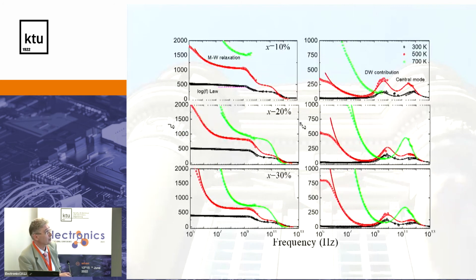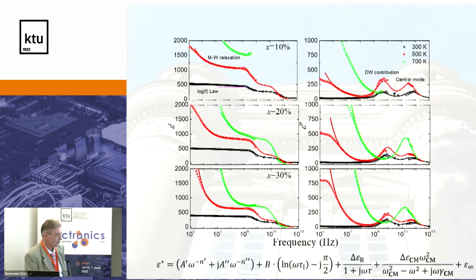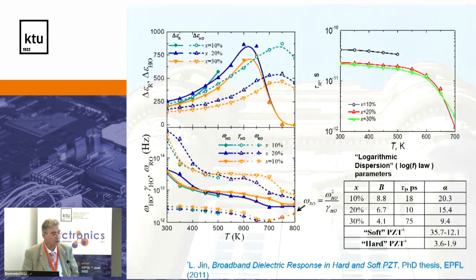First, we can look at the dielectric dispersion, and we can see a very broad frequency range. We measured up to terahertz, the whole dispersion. So conductivity part, dipole part, and further on will be the lattice part of infrared, but we stopped at that. And we have 3 different dispersions. And to explain such dispersion, you need to add a conductivity part, you need to add a relaxation part, and you need to add some soft mode with damping and so on, which goes in this part. So it's a damped oscillation, not a relaxation. And of course, you can get from these measurements all the parameters: contribution to the electric permittivity, relaxation time, damping, frequency, so all the necessary parameters which you need for applications.